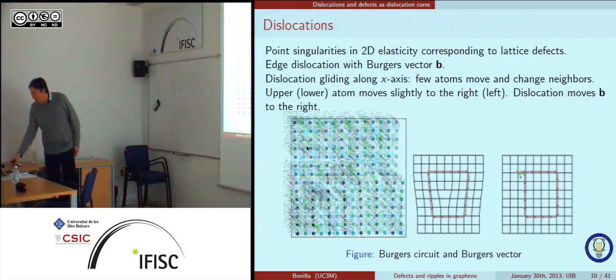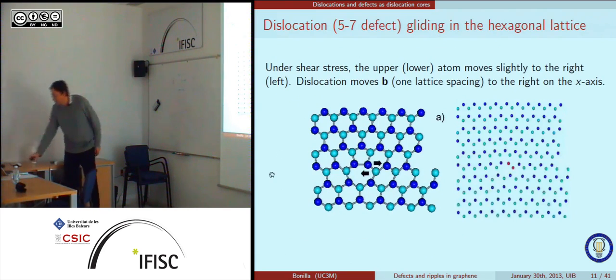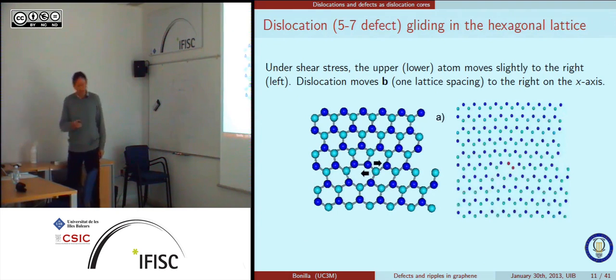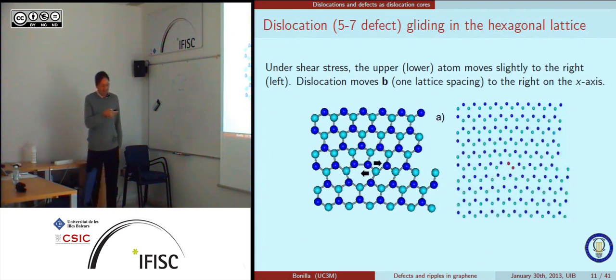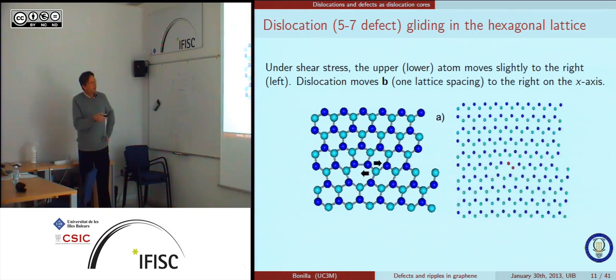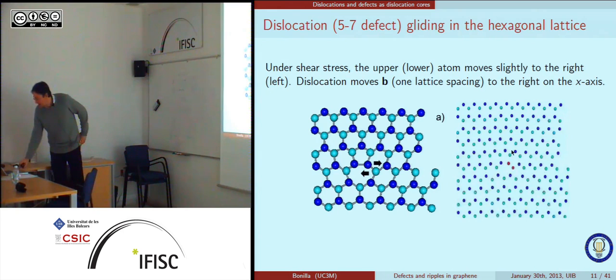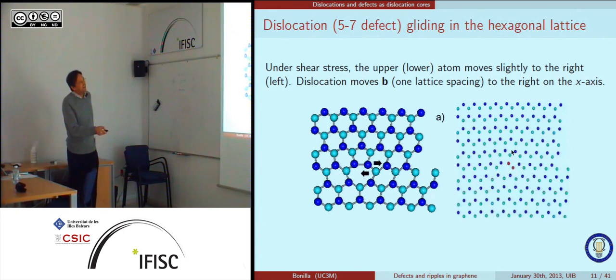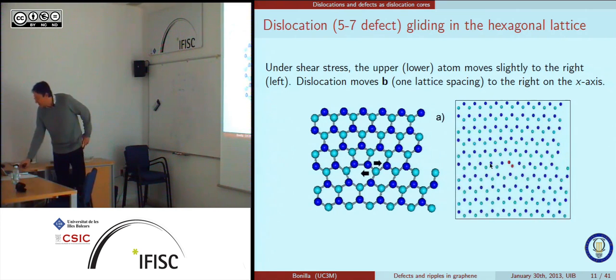It is easy to see that in the square lattice. In the honeycomb one, it's the same. One dislocation in this case is one pentagon and one heptagon. If you move this atom a little bit, you can perceive that as a motion of the dislocation, same as before. Here these two atoms are the ones that are going to move. You have a pentagon here and a heptagon there. Now these two are going to move, and you'll perceive that as the motion of the dislocation.